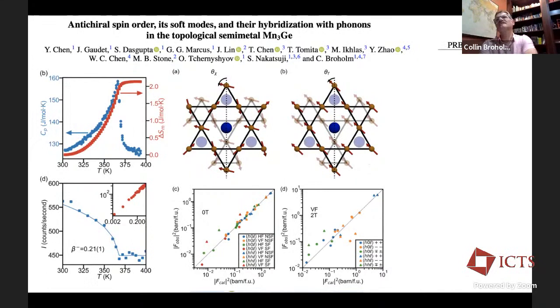And so you could say that this antiferromagnetic order must come along with a little bit of ferromagnetism. Energetically, it doesn't seem to be particularly favorable, so it's a very small component, but it cannot be fully extinguished because it has the same symmetry. So it's a Q equals 0 antiferromagnetism, and it furthermore transforms as a ferromagnet. And so in a sense, that's why it has this impact on the Dirac points of splitting them apart into Weyl points, because it really is behaving, if you will, like a ferromagnet, but it doesn't have the magnetic dipole moment.